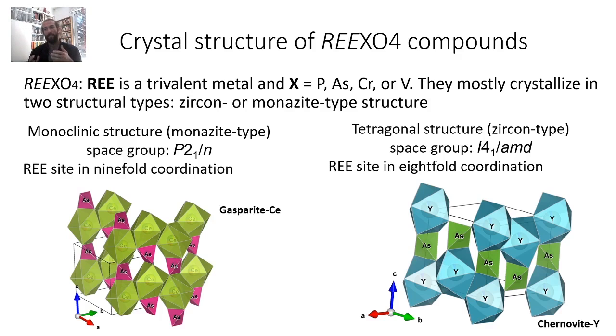The phosphates and the arsenates that I mentioned can be described by the general formula REXO4, where RE is a trivalent metal from the lanthanides series, or yttrium or scandium, and X is phosphorus or arsenic. They mostly crystallize in the tetragonal or in the monoclinic crystal system, and both the monoclinic monazite type crystal structure shown on the left and the tetragonal zircon or xenotime type crystal structure shown on the right are composed of rods running along the c crystallographic direction, formed by the alternation of RE coordination polyhedra and tetrahedra, the arsenic or phosphorus tetrahedra.